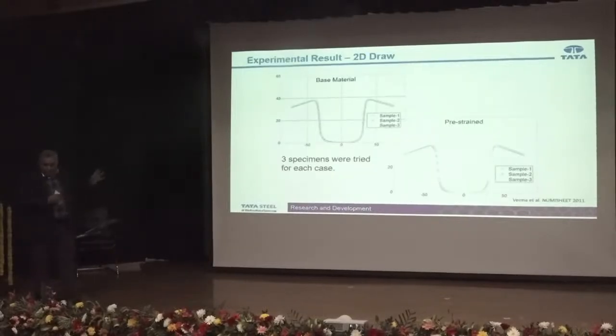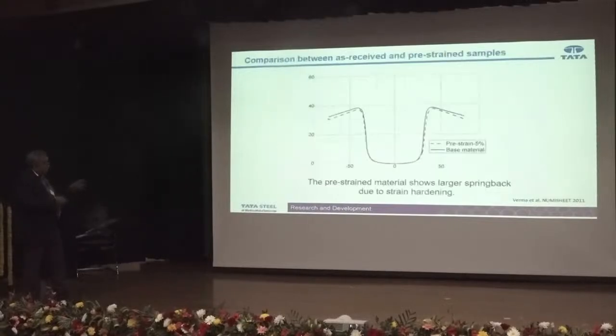Now the simulations were done. So these are the experimental results. Three samples were tested just to check the repeatability, and the repeatability was very good. And then this is the pre-strain. Here also three samples were tested and the repeatability was very good. Then the experimental comparison between the two was done only for the shape, and you can see here the pre-strain has higher springback. The reason is that because of the pre-straining and strain hardening, the strength has increased, and since the strength has increased, the springback will be higher.